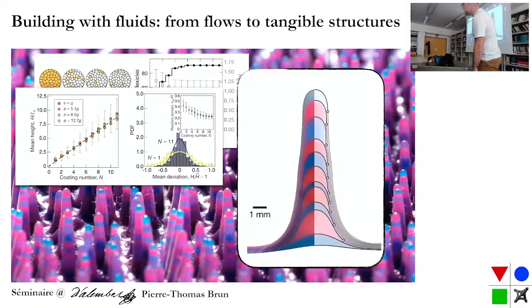Okay, but what are those? You can take one, slice it in the middle, and you see that we applied multiple coatings, and there are a number of things that you can observe. The first thing is that you sort of alternate big droplets and small droplets, but it's a bit of a chaotic process in this case. However, on the edge of the drop, there is always a very thin and uniform film. So you're combining a thin film, which is quite uniform, to a pendant drop, which is not uniform.